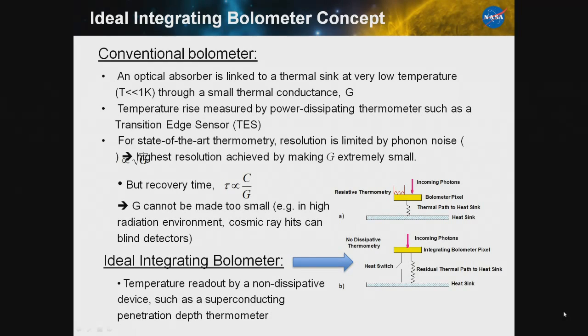For state-of-the-art thermometry, we're able to push the read noise down so that the resolution is really limited by phonon noise. Anyway, the point is that it's proportional to the square root of the conductance G. And so your highest resolution can be achieved by making G extremely small. Unfortunately, G is inexorably linked with the detector's recovery time. And so you can't make G too small, particularly in high radiation environments, or cosmic ray hits will blind your detectors or at least degrade them. And this is a current problem for Planck right now.